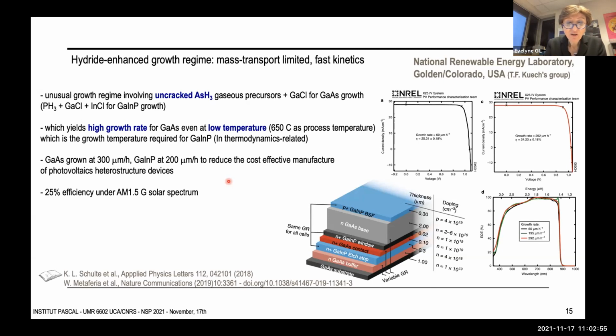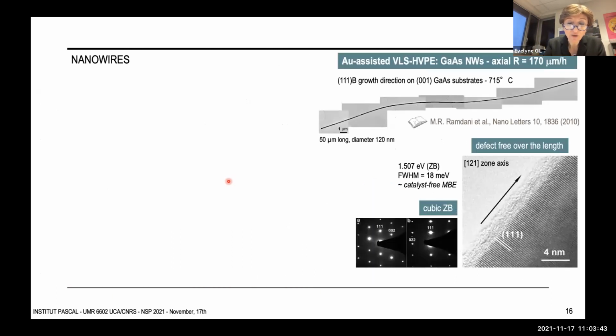Another way to reduce manufacturing costs of III-V photovoltaic devices is to move to cheaper silicon substrate and to benefit from larger wafer size, but also to grow less material in volume, namely to grow nanowires, even if Anna Fontcuberta showed yesterday that maybe the math was not necessarily as good as expected. And for nanowires to take advantage of physical properties, which can be modulated as a function of the geometry, surface to volume ratio of the nanowires, and also spacing between nanowires when they are arranged in periodic arrays, as depicted yesterday or in his review papers by Ray LaPierre. So let us move to nanowire growth.